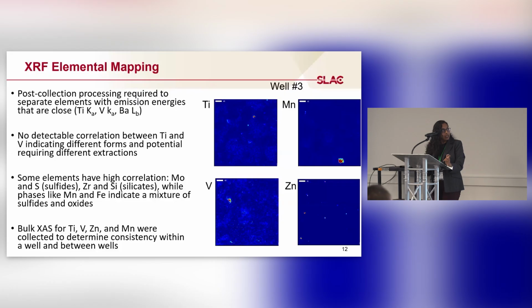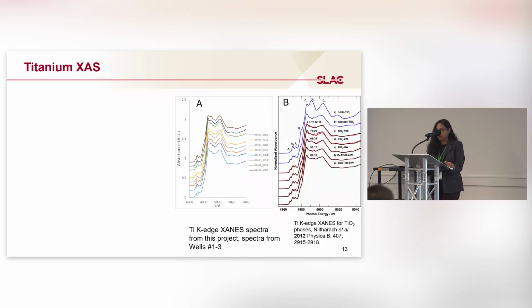So going to the titanium X-ray absorption spectra. X-ray absorption spectroscopy uses the synchrotron, and how we can understand the data from it is that it's a very fingerprint sort of spectra for each element, and it depends on the oxidation state and the environment of each element present in your sample. So it's a very fingerprint analysis. If you look at the left side, it is the image of my sample, the spectra that was collected, and on the right-hand side is a reference image.